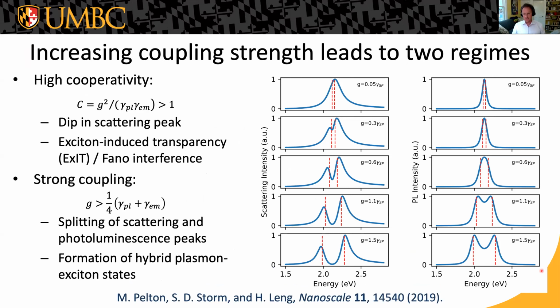And again, this is not an exact quantitative theory, but it's good enough to explain most of what we can actually see experimentally, and it also gives us a good handle on what's going on in these systems as we change these parameters. So here I've just plotted, using typical parameters for plasmon line widths, exciton line widths, and oscillator strengths at room temperature, what the scattering spectrum here on the left and the photoluminescence spectrum on the right would look like in these systems as you increase the strength of the coupling between the two of them.